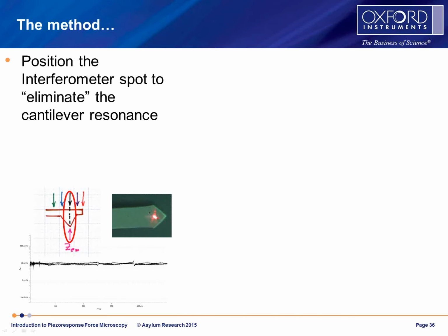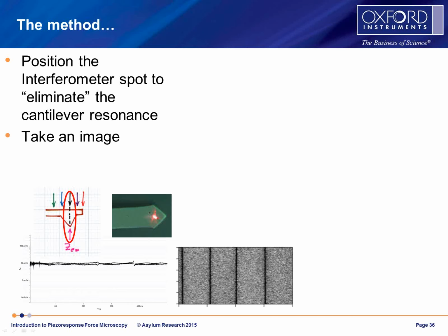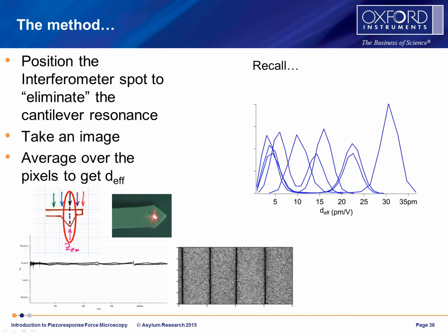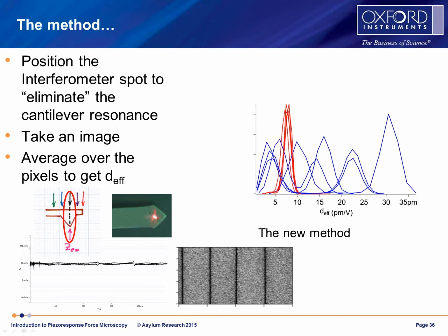So this interferometer result suggests a new method to try to quantify our AFM response. And so we took this new method and applied it to the periodically poled lithium niobate. The new method is that you position that interferometer spot to eliminate that resonance effect, so that is putatively right above the tip position. And then at that point in time, you take an image, and you can see this image here is another image where the response over the domains is equal and looks nice and clean. And then you calculate the d effective and make a histogram of it, just like we did in the original work. Now, if you recall, this was the optical beam results. We applied this method over the very same domains on the very same cantilevers with the interferometer method, and the results are here. So quite an improvement.